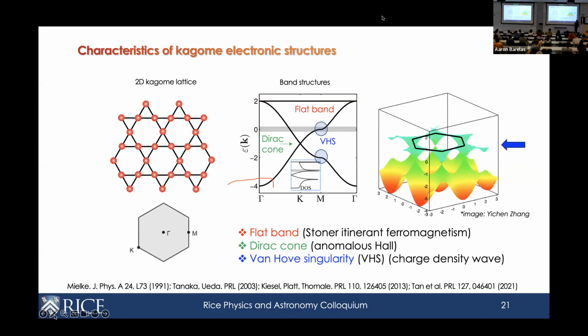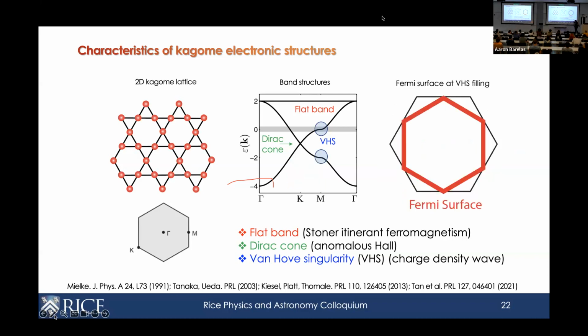The third one, which is actually really important and which has really captured the heart of many people in recent years, is this object, which I circled in blue here, and which is essentially a saddle point, and it's also called the Van Hove singularity. It's a saddle point because you can see the band curvature is down and up along 2 different pathways, which means that this looks like a saddle, and in the 2D limit, the density of states will give a divergence at this energy. And it turns out, if you tune your chemical potential to one of these Van Hove singularities, which is the case here, you get a very special Fermi surface. This is plotted in 2D.